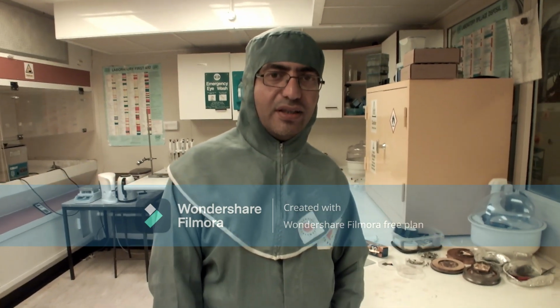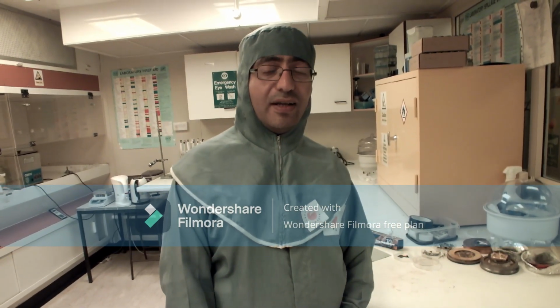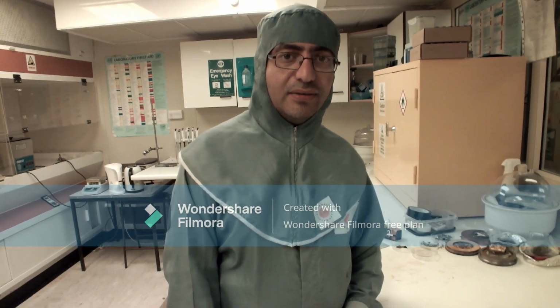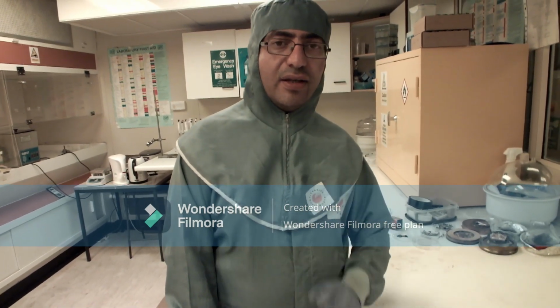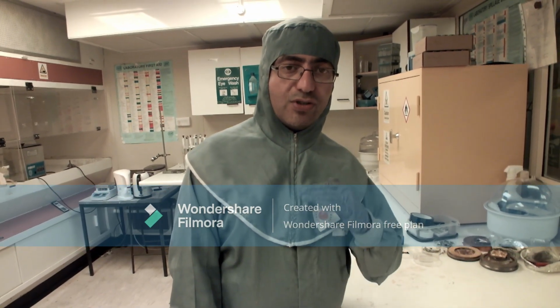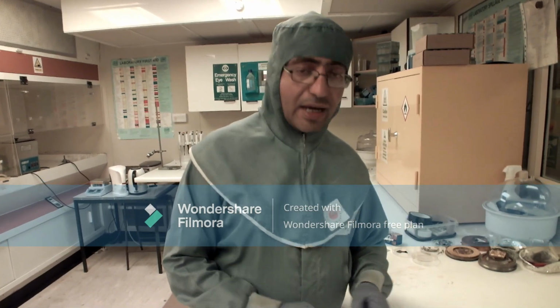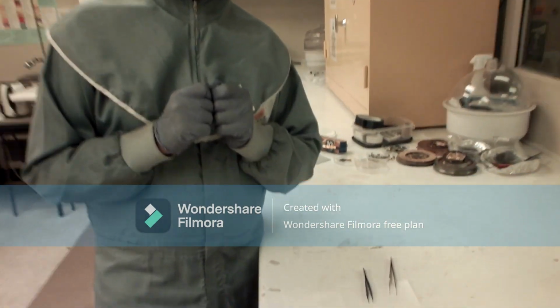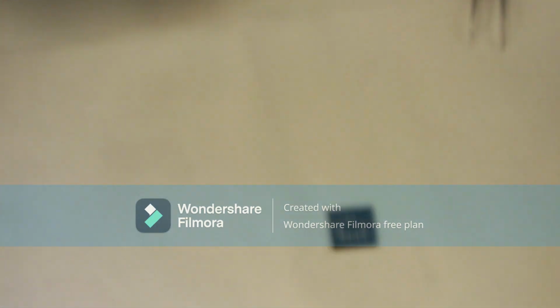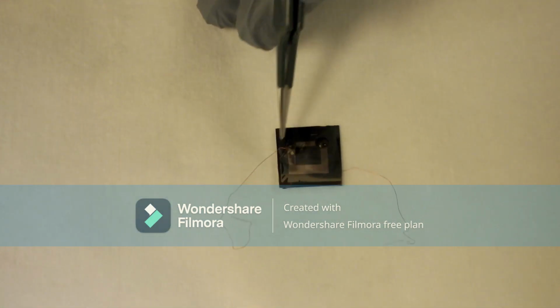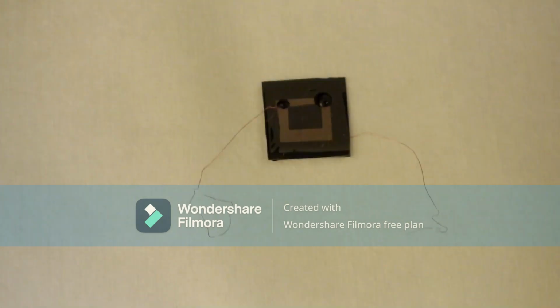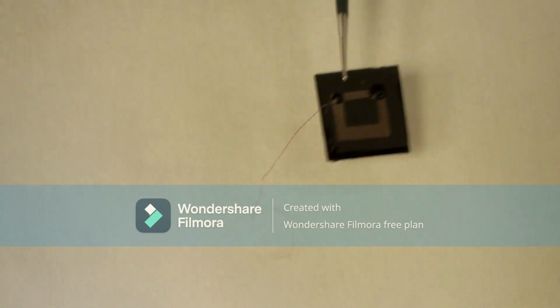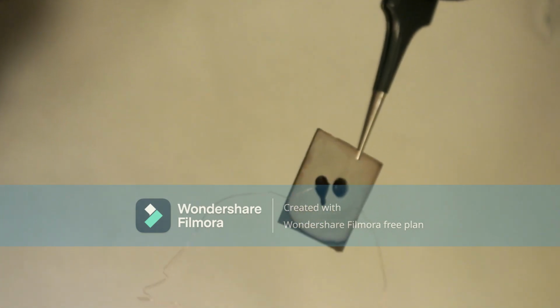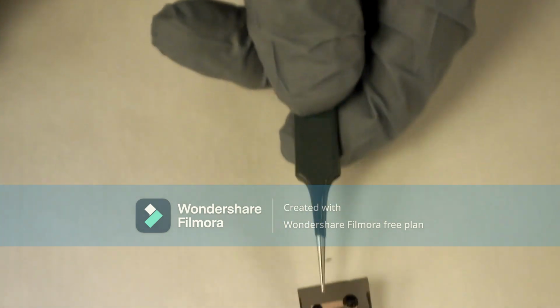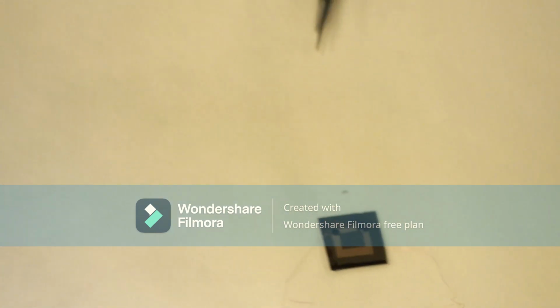So after we did the transfer process for the graphene with the PMMA layer, I removed the PMMA layer and kept the graphene on the center of the silicon, which will make the Schottky contact. Then I place 2 wires to make the proper contact. As you can see, the graphene is in the middle and 1 wire on the top, on the gold, for the front contact, and the second contact on the back side. This one is for ohmic contact. Now my sample, the graphene silicon Schottky junction solar cell, is ready for measurement.